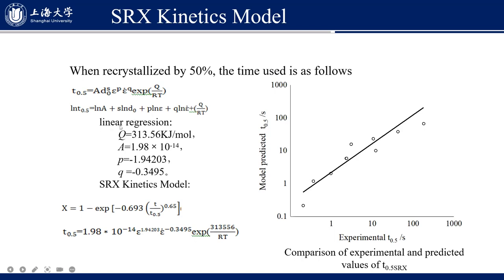And by linear regression, Q, A, p, and q are obtained. And the SRX, say, static recrystallization kinetics model is established as follows. And here is the comparison of experimental and predicted values of t0.5 for static recrystallization. It's quite well fitted.